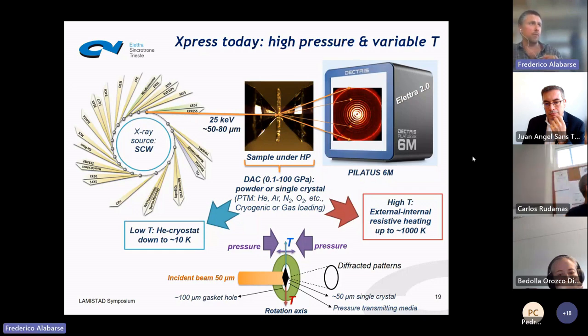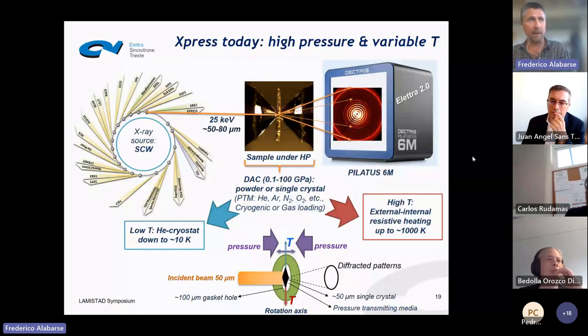We are working today with an X-ray source of a superconducting wiggler, which gives us a fixed energy of 25 keV. The beam spot varies from 50 to 80 microns. With this beam spot, we can perform experiments up to 100 GPa. We work with both powder or single crystal, collected using a Pilatus detector, which is one upgrade of the beamline. We already received this upgrade. This is already Elettra 2.0 arriving at the beamline stations. It's a very good detector.